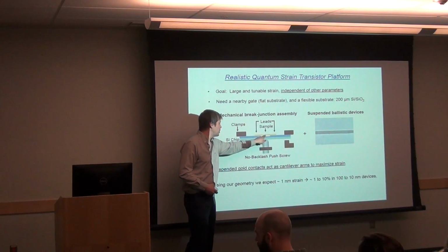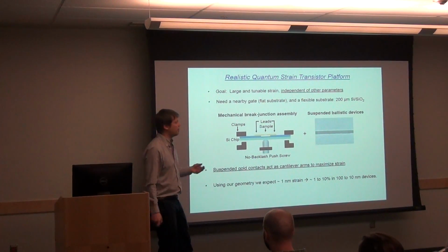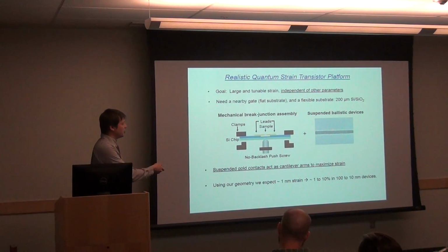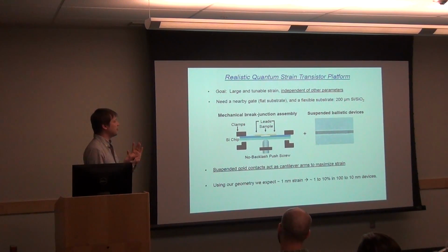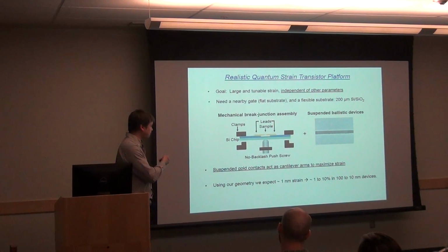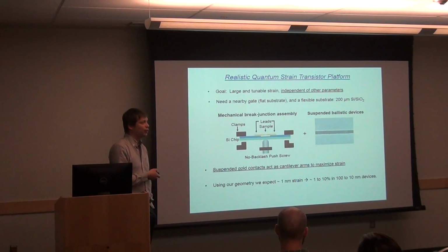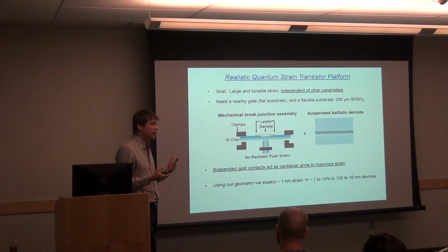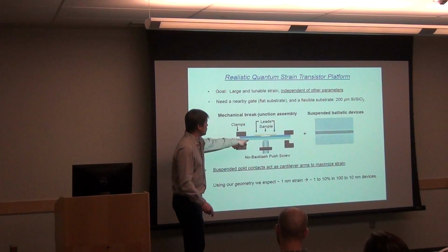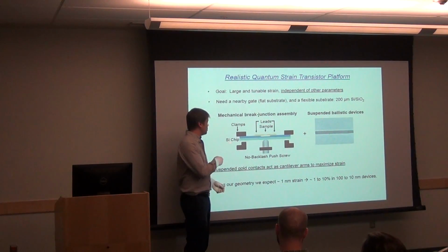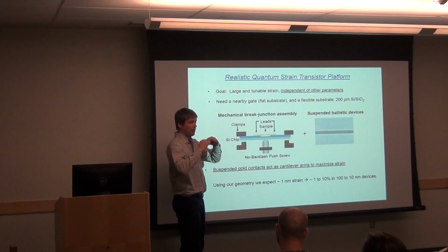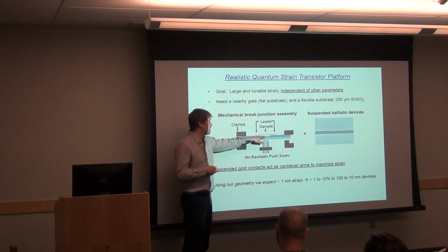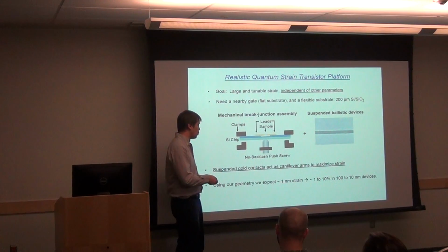If you apply a gate voltage, because this is such a short device, it would just be 50 or 100 nanometer, in this case it's 100 nanometer, the strain applied from the gate voltage is negligible. So it's completely independent from other parameters in the Hamiltonian strain. This is inside a cryostat that goes to very low temperature, very high magnetic fields. This is on a silicon chip which you might think shatters, and it does if you bend it too much, but the trick is that we're using long cantilever arms. So this is a very thin chip of silicon, so you can flex it a little bit, and by flexing it just a little bit, you can stretch this by about 1 nanometer.